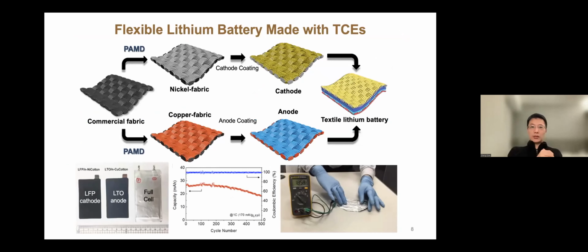For this textile composite electrode, basically we need to make a metallic textile in the first place. So we take whatever base substrate it is, and it varies, made of textiles, and then deposit some kind of metal, for example nickel for the cathode current collector and copper for the anode current collector. On top of which we coat the cathode and anode slurries, and then assemble a flexible cell. The cell looks typically like this. This flexible pouch looks similar to what we have in pouch cell assembly.